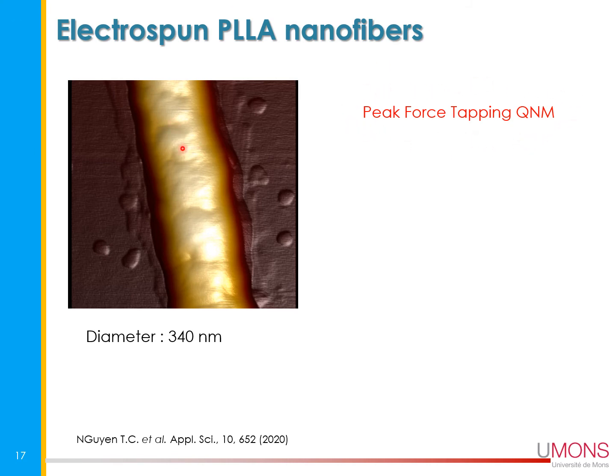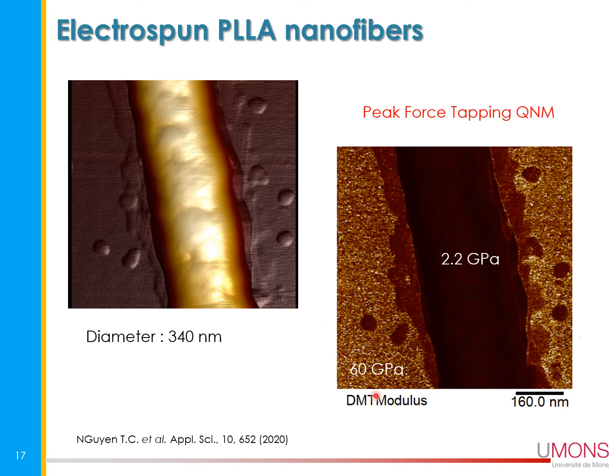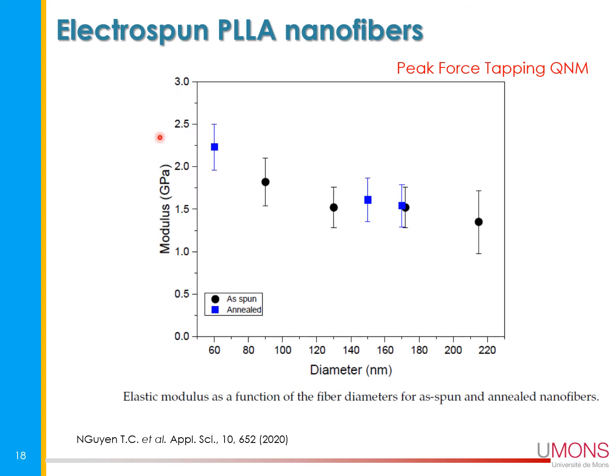As I said before, thanks to the PeakForce tapping, it's possible to get the mechanical properties. This is another fiber which is larger, in this case 340 nanometers, and this is the mapping of the rigidity modulus. We have roughly a fiber which is about 2.2 gigapascal, while we have here the glass which is, as we know, about 60 gigapascal as a rigidity modulus. You can find all the details in the recent paper from Nguyen about this work. So by collecting the mechanical properties with different diameters and different situations, as-spun or annealed, you have the evolution of the mechanical properties, which is important in this case, versus the diameter of the fibers.